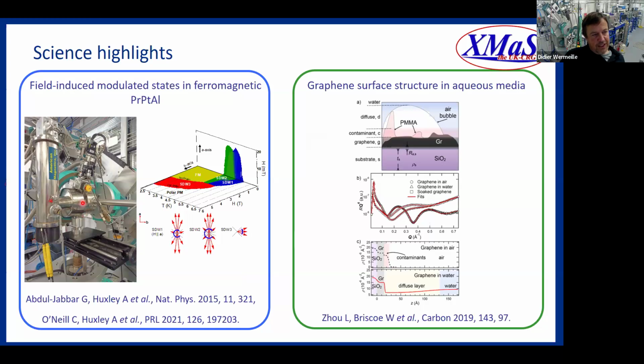So the 4 Tesla magnet, very low temperature. You can see like we went down to 1.8 Kelvin, studying the quantum critical point in this praseodymium platinum aluminum sample. And there's a very rich spin density waves forming depending on the magnetic field, the orientation of the sample inside that magnetic field, and the temperature. And so that was possible over a few beam times with these 2 publications, and some